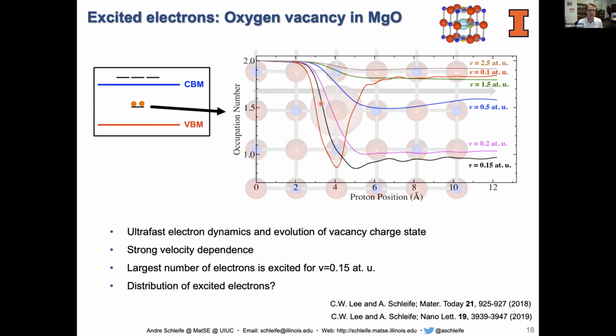If you don't like this real space representation, you can look at the energy of these states. You see in this material you have a valence band maximum of magnesium oxide and a conduction band minimum, and then somewhere close to the middle of the band gap is this defect state, which in its ground state is occupied. Okay, so now we start our time-dependent simulation where we shoot a proton on this black arrow through the material near the vacancy. Okay, and we plot as a function of time the occupation number of this defect level. So how does that change as the proton moves past this defect?